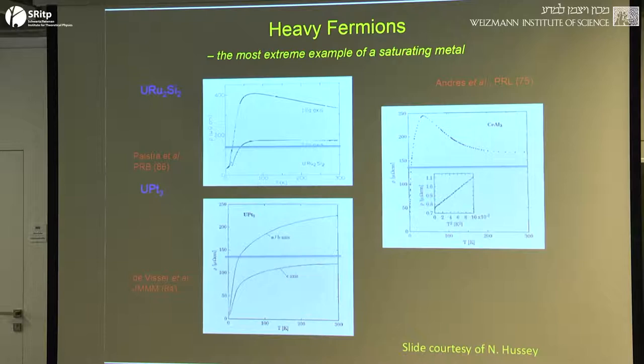This is uranium platinum 3, and this is cerium aluminum 3. Here the resistivity saturation has somewhat more structure than it does in the A15s. The resistance overshoots its asymptotic high temperature value and then settles back down to some value that's close to the quantum of resistance.